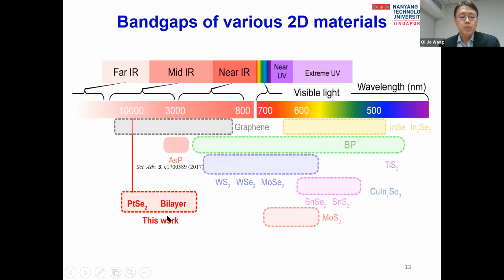So in this work, we first identify a new material, PtSe2, and we discover that a bilayer of such material has a narrow bandgap that can cover a wide wavelength range in the mid-infrared region, from around 10 micron down to the visible range.